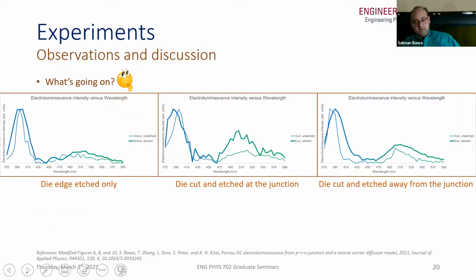So what's going on? One way to figure this out is let's try to put these electroluminescence graphs side by side. So when the die edge is only etched, there really is no change. But when the die is cut and etched at the junction, we see the green peak relatively rise. And when the cut and etch is away from the junction, we see some rise in the green light.